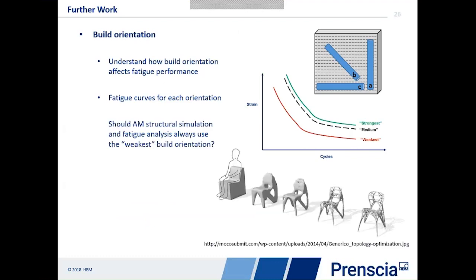And if they do have a weak and a strong direction, is it sensible to just always assume the weakest curve and design on that basis? In order to do that, we need to understand what degree of scatter there is in those curves, and also how that's affected by those heat treatments, because certainly our initial look-sees seem to suggest that the heat treatments afterwards, the HIP treatments, are helping us to homogenize these materials so we don't get this orientation effect. But this is something that we really do need to research more fully.